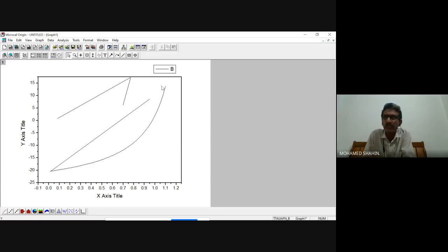And one of the most fragile systems I have seen is ethyl benzene. It is very difficult to crystallize. Fragile systems will generally crystallize very quickly. Strong systems will be very slow, a very stable glass former. Like, crystallization is very small.